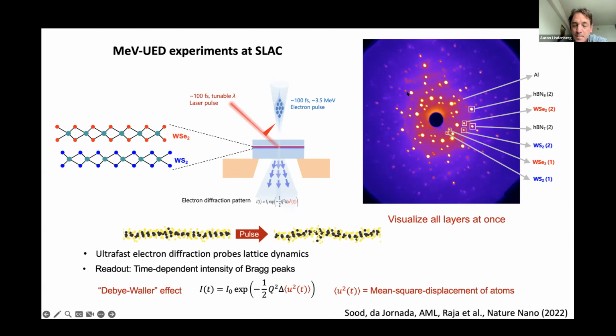Essentially, what we're going to be doing is the simplest possible thing. We're going to be looking at the intensities of these particular Bragg peaks. I won't go into a detailed explanation, but I think many of you know that in any solid, if the atoms are jiggling around more as the temperature heats up, this is going to reduce the intensity of the Bragg peaks just from the increased disorder in the sample. This is known as the Debye-Waller effect, and this simple model relates the intensity of the Bragg peaks to the mean square displacements of the atoms, which in turn are related to the temperature of the structure. So through this type of analysis, we're able to make plots of the time-dependent temperature in each of these systems.